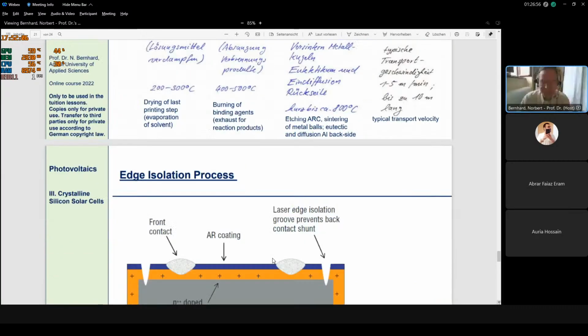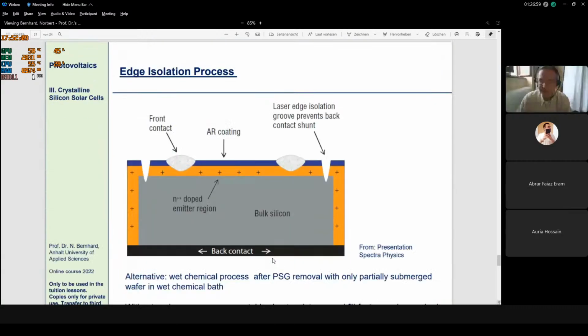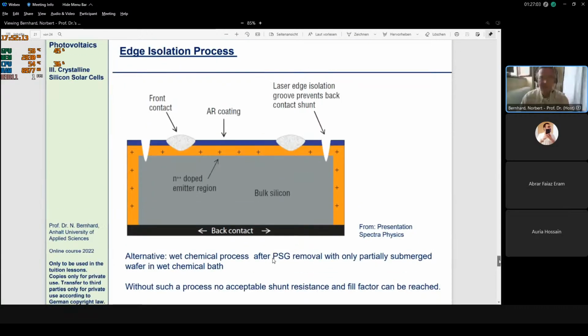Okay, then there is a last process which was not mentioned on my initial foil, but which is also very important. It's the so-called edge isolation process, and it's shown by this schematic. You see, in principle, we have the p-doped region, we have the n-doped emitter, and the n-doping, of course, is also at the edges because we did not protect the edges. And here we have the back contact, and you see, in principle, we would have a shunt along the edges from the front side to the back side. And therefore, we have to interrupt this shunt, and this can be done by a laser cut. If you just make a laser cut of a trench which is deeper than the PN junction, it interrupts this shunt.